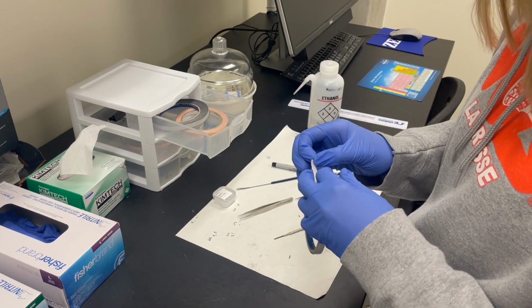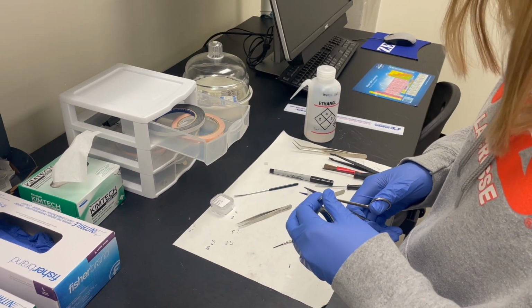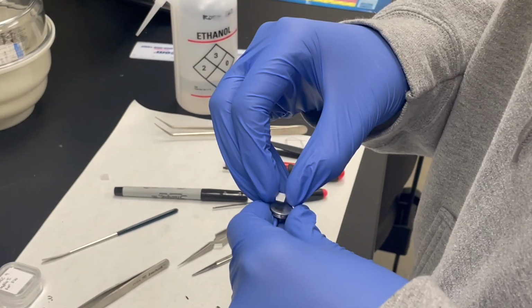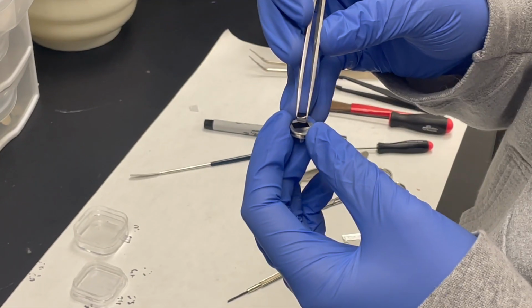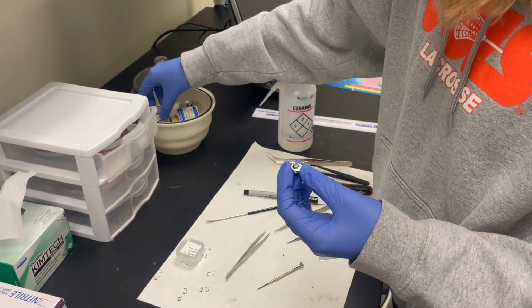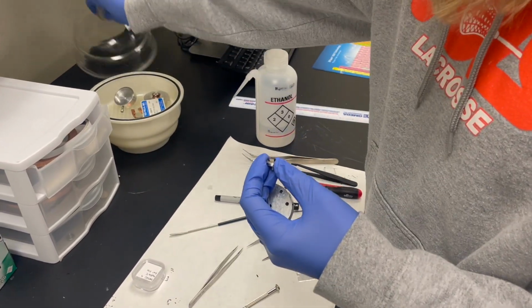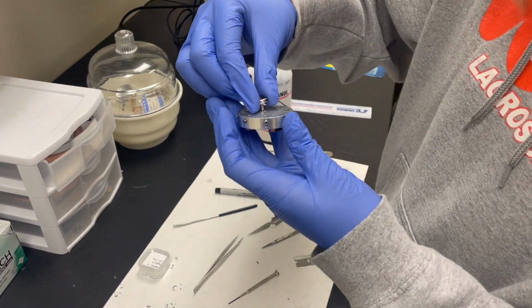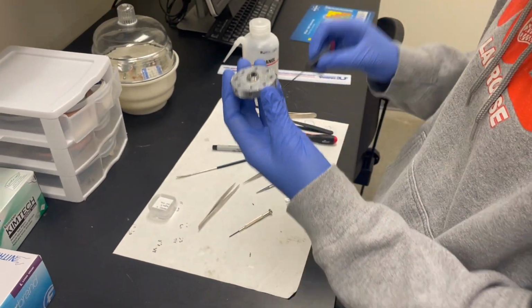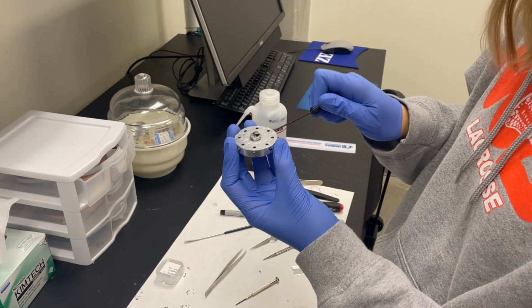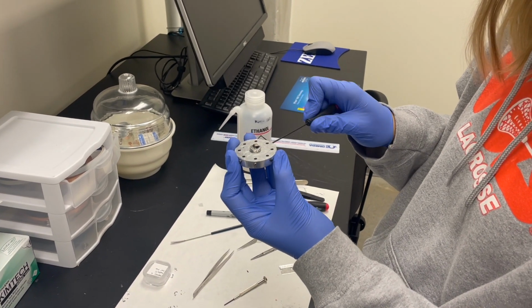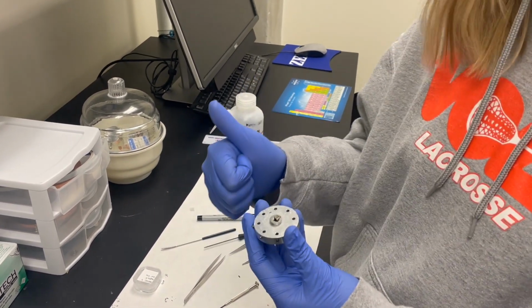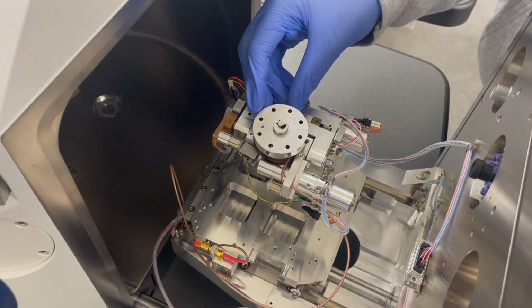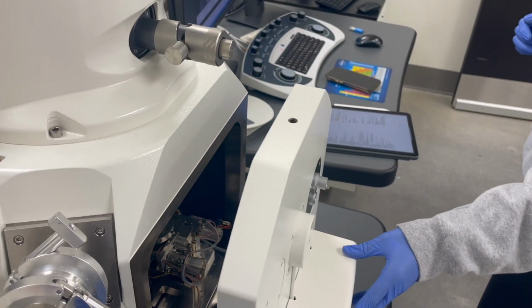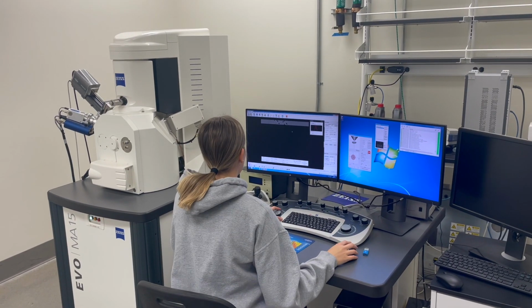Pre-irradiation, we also do a variety of preliminary characterization. To prepare the sample for microscopy, we attach the sample to an SEM stub using a small piece of carbon tape. Take the SEM stage out of the desiccator and place the stub in one of the several stage positions. For ease of imaging, we chose the center slot. Use the small screwdriver to tighten the grub screw, securing the stub. Load the sample stage into the SEM and pump the vacuum. With the proper SEM training, you're ready to image your sample.